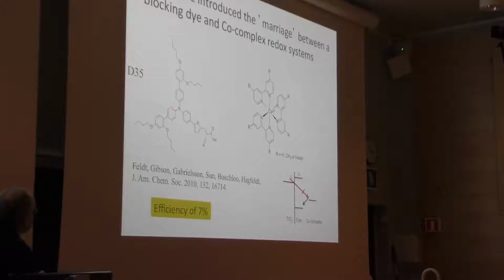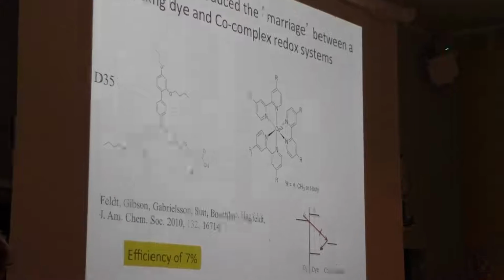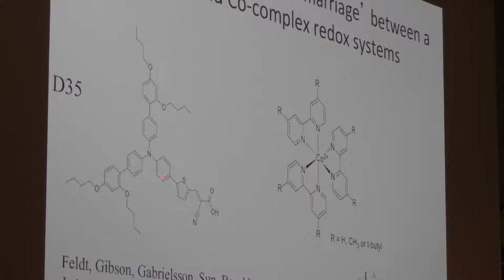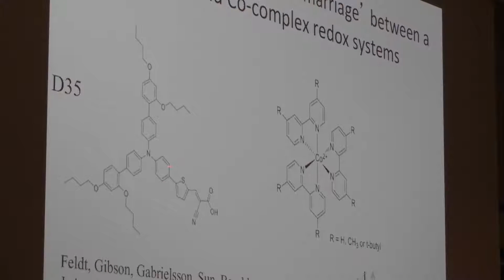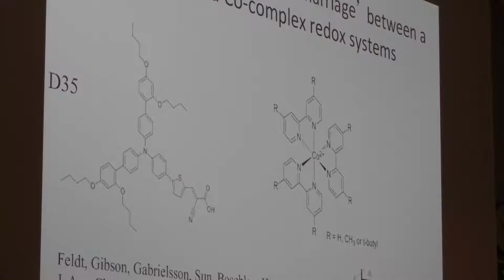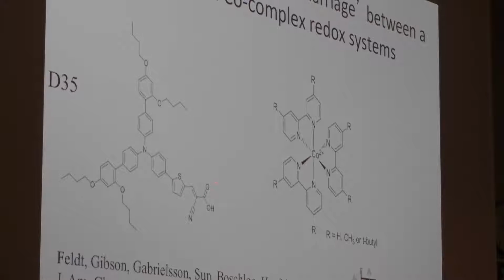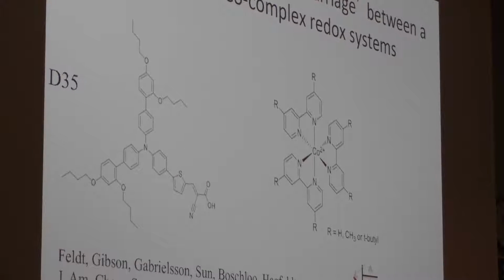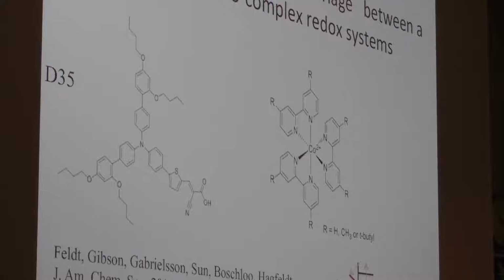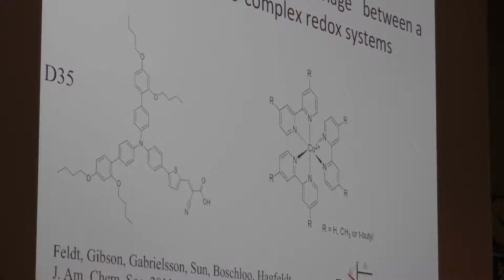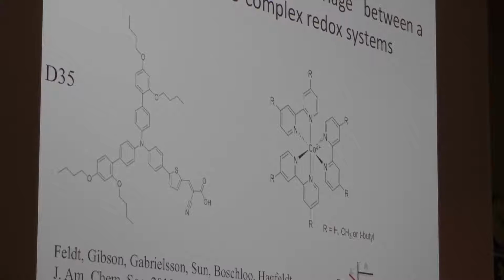We made this dye. It's an organic dye, in collaboration with Licheng Sun at KTH Stockholm. It's a triarylamine unit. This is the donor group. This is the linker, as we call it, and this is the anchoring group. Now the problem with these organic dyes is normally that they aggregate on the surface. So the design we did to avoid aggregation was to bring in these alkoxy groups. So the idea was really to break aggregation with these alkoxy groups, so that they point in different directions. That we could observe was the case, so we were happy about that, but we had a bonus effect.